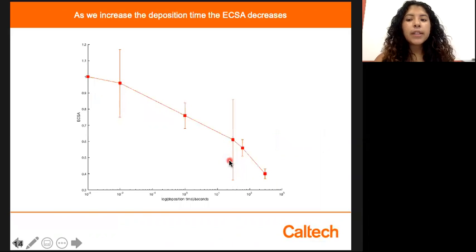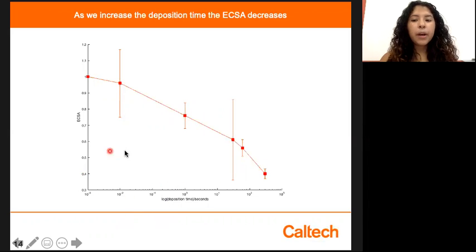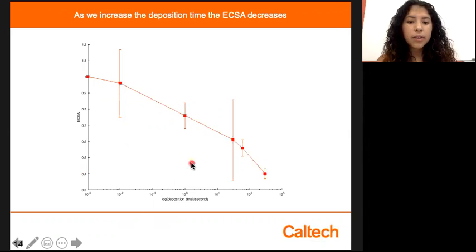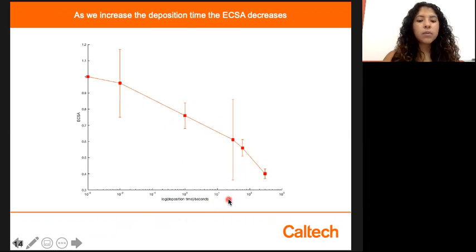When we plotted the ECSA versus the log deposition time, we found that there's an inverse relationship between deposition time and ECSA. One hypothesis for this relationship is that the longer we deposit this organic film, the thicker it becomes. And because the film is non-conductive, it's covering some active sites where the current could be flowing.